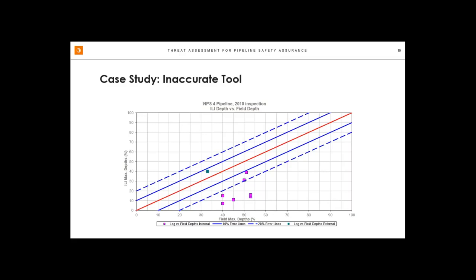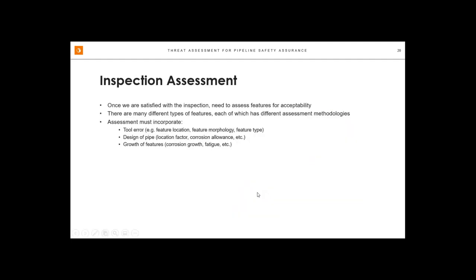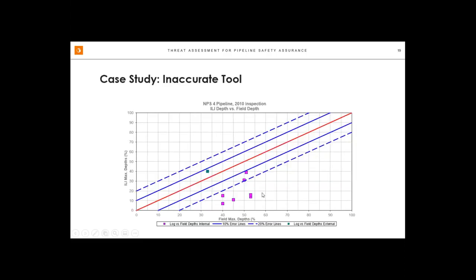But as we did the QA process and we compared it to some of the excavations, what we found is some tremendous undersizing. We had some features at the bottom here which were undersized by almost 40%. The ILI tool called them at about 13–14% deep, and they were found in the field to actually be 53% deep.